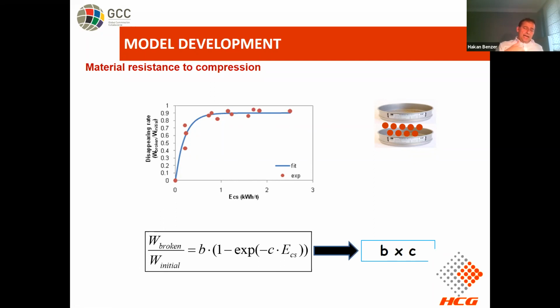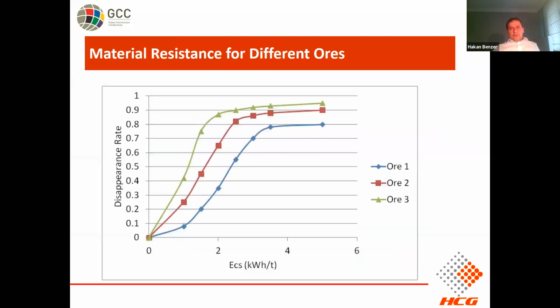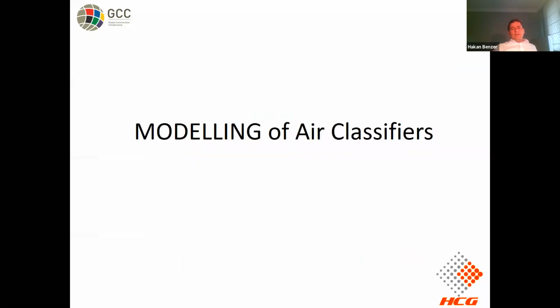So once we have the material, if we run a piston and die test, we can calculate both the breakage distribution function and the material softness, which goes into our model structure as an input. You can see the material resistance for different ore types we measured.